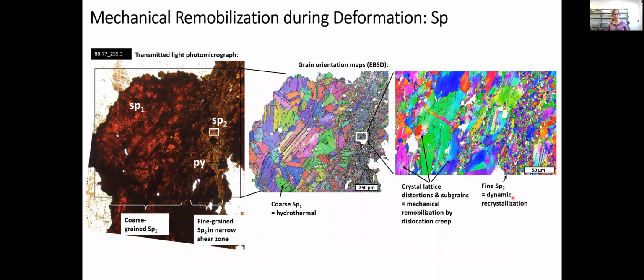Now, if we look at the EBSD maps, we can see that the coarse dark sphalerite is very coarse grained. That is a single grain, and it's cut by a lot of twins. And the fine-grained sphalerite, the pale sphalerite, is so fine grained I had to do another EBSD map of that area at a much higher resolution. And now you can finally start making out individual grains. They're really just a few microns across. And again, looking at the internal distortion and recrystallization, we can say that sphalerite probably deformed by dislocation creep and experienced dynamic recrystallization to form these really fine grains.